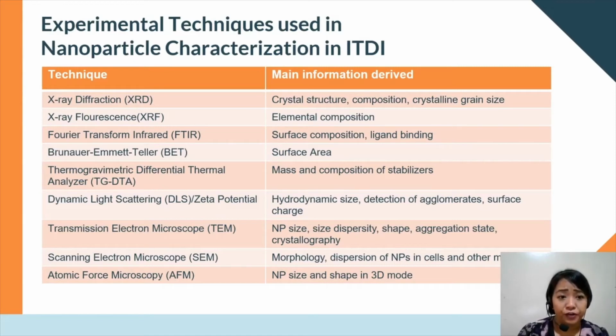For thermogravimetric differential thermal analyzer, or TGDTA, we can measure mass and composition of stabilizers. For dynamic light scattering, DLS, and zeta potential measurement, we can identify hydrodynamic size, detection of agglomerates, and of course the surface charge of the particle.